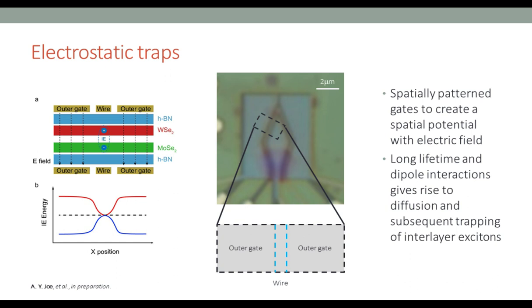So what we did next is we made a new sample, but now we have 3 different spatial areas to change the electric field. So we have 2 outer gates, and we have a very narrow wire gate. And so in this wire, by changing only the outer gate electric field, what we can actually do is change the interlayer exciton energy either up or down. Since these excitons are charge neutral, you have to actually change the energy of the excitons rather than changing, for instance, doping or carrier density like you would do in a typical quantum dot.